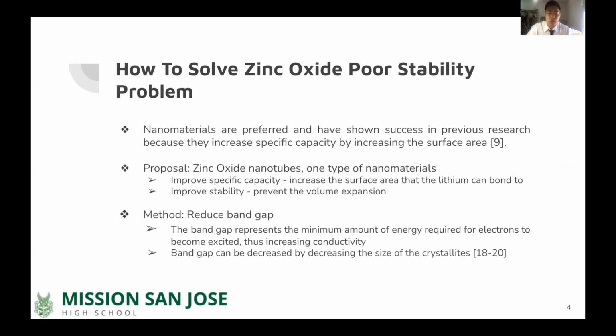So nanomaterials are preferred and have shown success in previous research because they increase specific capacity by increasing the surface area. It has been shown that zinc oxide can be made into many different materials such as nanotubes, nanospheres, and other shapes that improve its performance. This also helps counter the volume expansion of zinc oxide, which is 228% for traditional zinc oxide materials. We propose nanotubes, which are very tiny tubes of zinc oxide, due to the success of previous researchers in finding especially promising properties that improve specific capacity and combat the weaknesses in zinc oxide. They increase the surface area that lithium can bond to, increasing capacity. They also help prevent the volume expansion of zinc oxide.